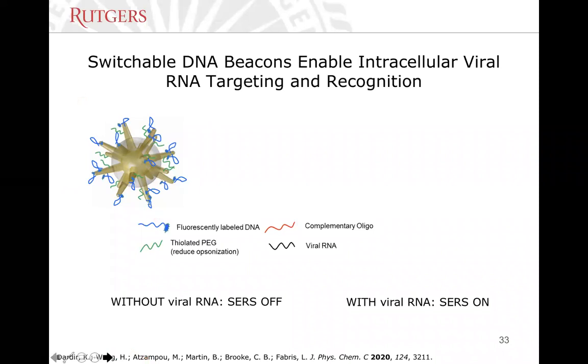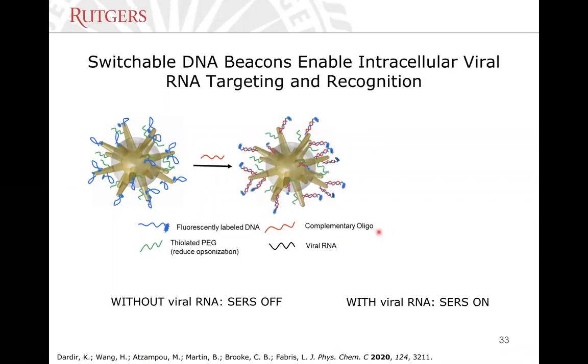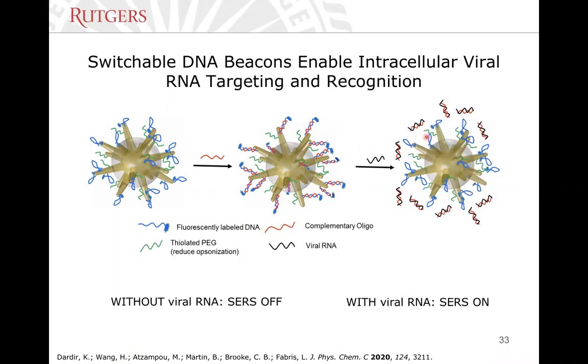Then we added a complementary oligonucleotide. We designed it in red, and this is made to hybridize with the blue beacon and stretch it out, so that the fluorophore is far, the SERS signal is quenched, and the fluorescent signal is on. Finally, we take this construct and we expose it to the virus. When this is exposed to the virus, the red oligonucleotide is designed to dehybridize from the beacon. The beacon is alone again, it folds back, the fluorophore comes close to the surface, and then we see the SERS signal all over again. So we go from on, off, on. Basically, we go from an off situation to an on situation whenever the virus is present in the system.